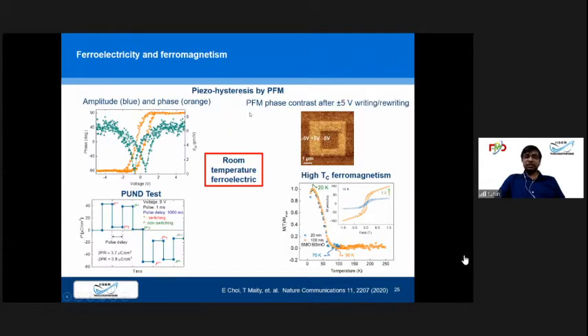So we measured the room temperature ferroelectric property. As you can see, this is a P-E hysteresis. Paraelectric materials give a straight line, so if we measure polarization against voltage, you get a linear curve. But we are getting a hysteresis loop. That means at room temperature the material has now become ferroelectric, which was initially paraelectric. And we can switch the polarization, so we can write and rewrite. So this is a kind of ferroelectric polarization.